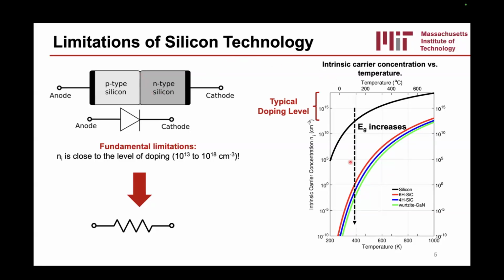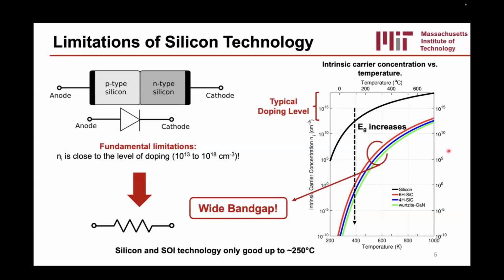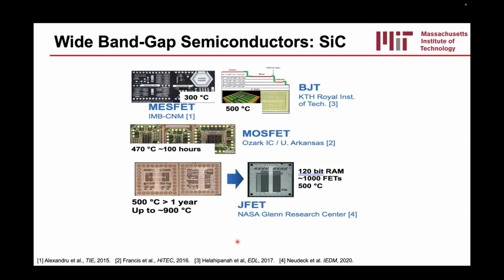But lucky for us, this intrinsic or background carrier concentration is also an exponential function of the band gap. And so that's where wide band gap semiconductors like silicon carbide or gallium nitride come in, and we can operate at least theoretically up to 1,000 Celsius. And we see this in practice too. If you try to buy a silicon or a SOI technology, it's almost always rated to at most 250 Celsius. So we need a wide bandgap material.